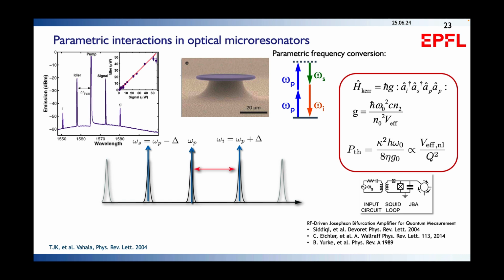And one aspect that's interesting about that process is that even though the Kerr nonlinearity is an exceedingly weak nonlinearity, the threshold for parametric oscillators scales inversely with the quality factor squared. And that is because this device has a nonlinear gain mechanism. So the higher the intensity, the larger is the gain. In a conventional laser, you have a 1/Q dependence. And so this implies if you have a very high Q resonator, you can really drive down the threshold of these parametric oscillations to levels of just a few milliwatts. And that was possible in this early work.